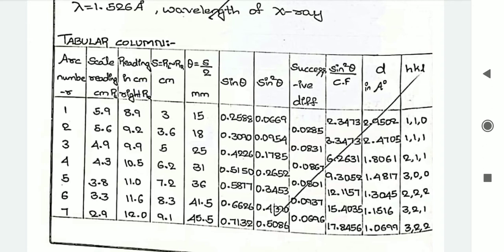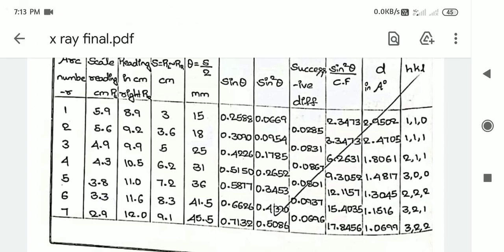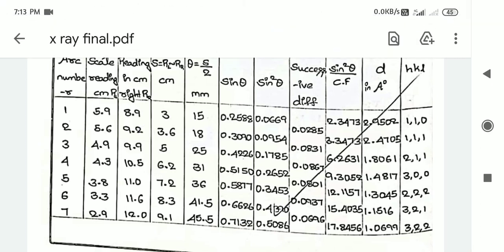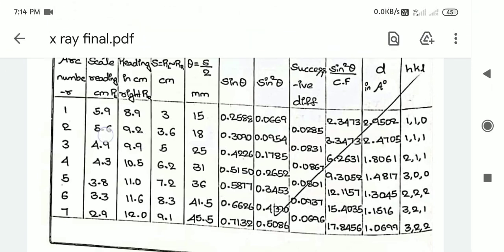Enter those readings in the tabular column. In the tabular column you can see arc numbers 1 through 7, with scale readings on the left-hand side and right-hand side. For the left-hand side, for example, the first arc reading is 5.9, second is 5.6, third is 4.9, and so on up to the seventh. For the right-hand side from the same position, for example, you might get 8.9, 9.2, and so on up to arc 7. To calculate S: S equals RL minus RR in centimeters. For example, the first reading is 8.9 minus 5.9 equals 3. Whichever value is bigger, subtract the smaller from it to get S.